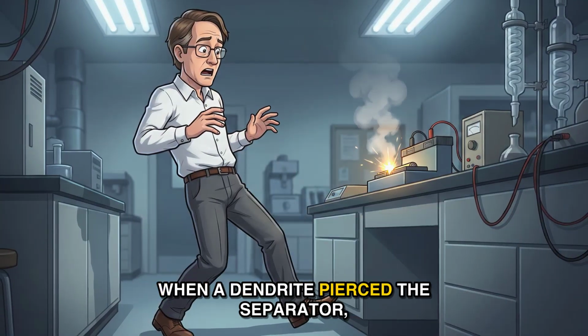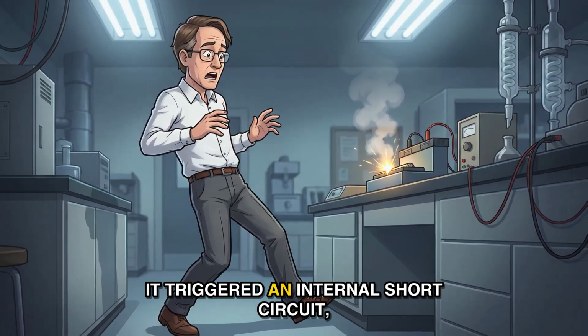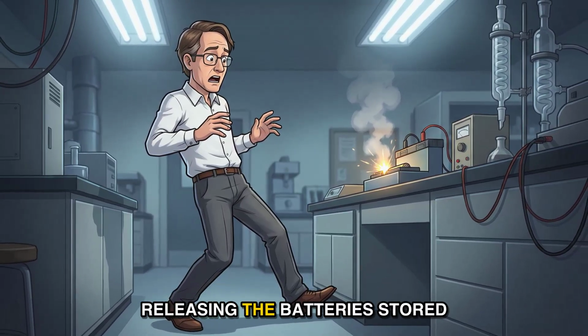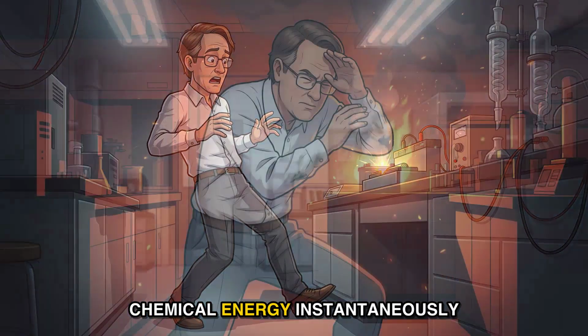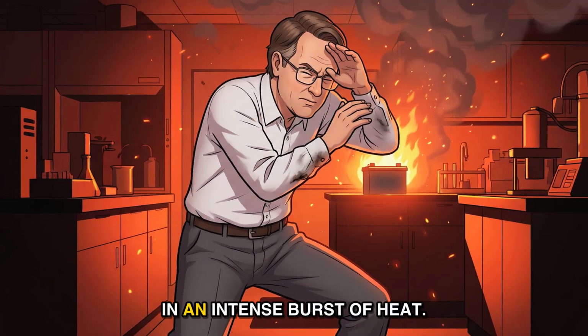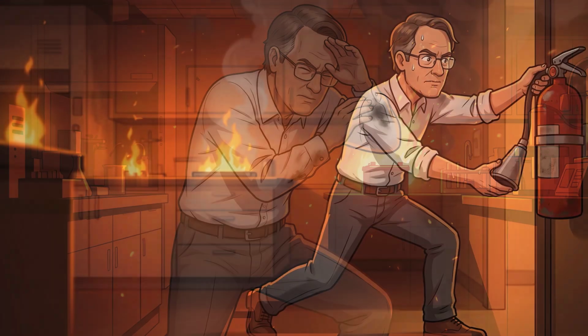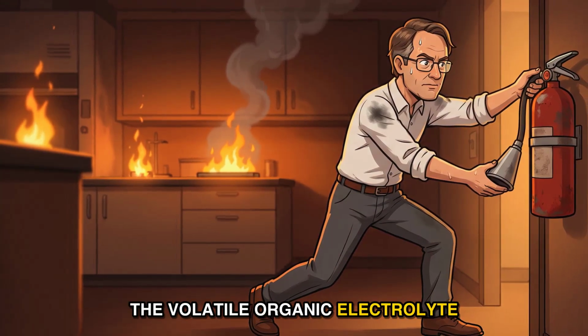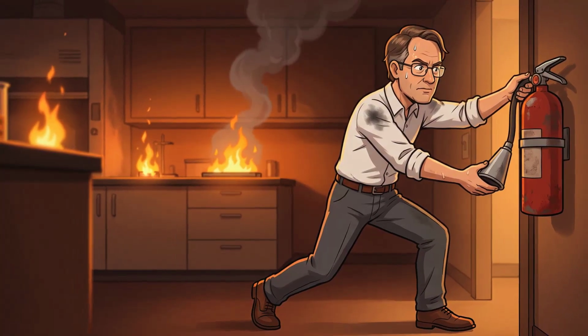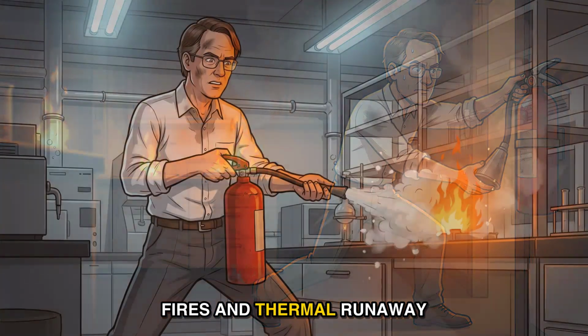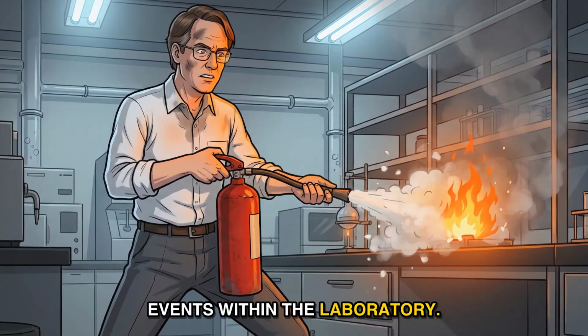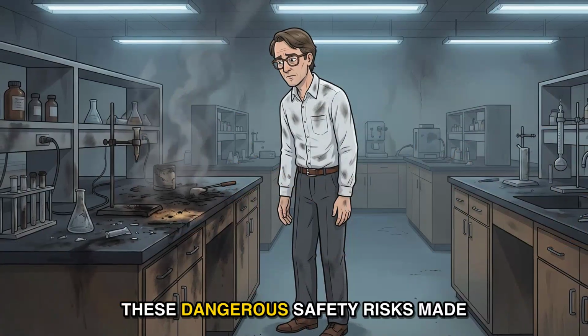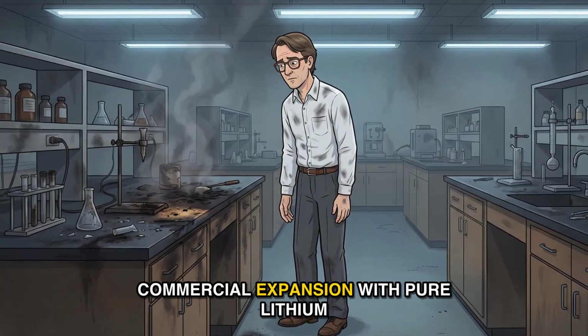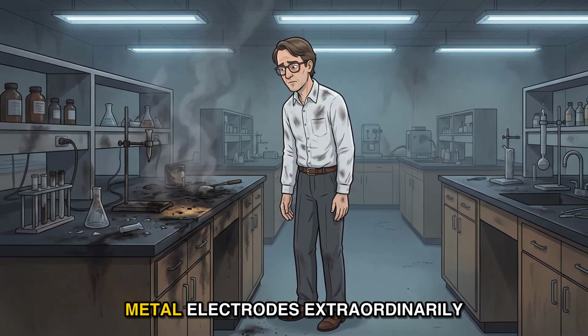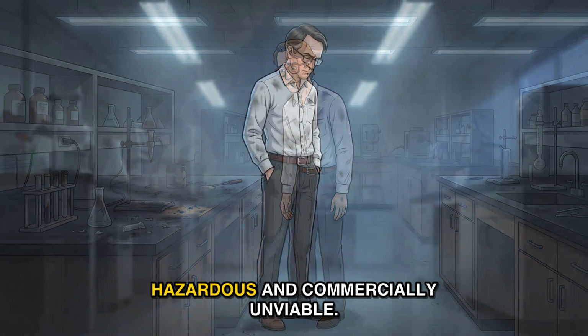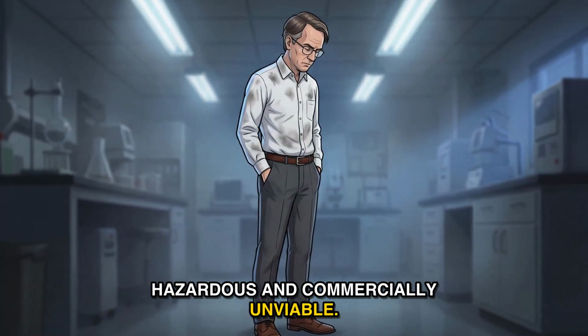When a dendrite pierced the separator, it triggered an internal short circuit, releasing the battery's stored chemical energy instantaneously in an intense burst of heat. The volatile organic electrolyte rapidly ignited, causing small fires and thermal runaway events within the laboratory. These dangerous safety risks made commercial expansion with pure lithium metal electrodes extraordinarily hazardous and commercially unviable.